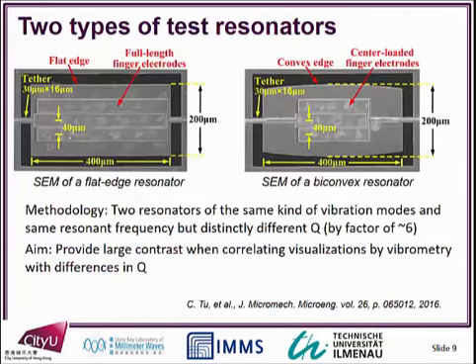The way that we thought we'd do it is to take two resonators which we know have very different Qs and should give very different profiles. Can we actually see these differences in the profiles on the vibrometer itself? One is just a normal resonator with a very flat edge. That's another one that's got a curved surface, and what that does, as we've seen just now, is concentrate the energy in the center. The difference is quite stark, on average as much as a factor of 6. And this has been measured over several devices, so it's quite consistent.